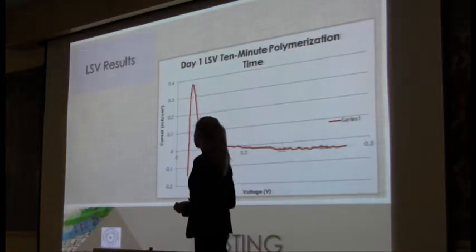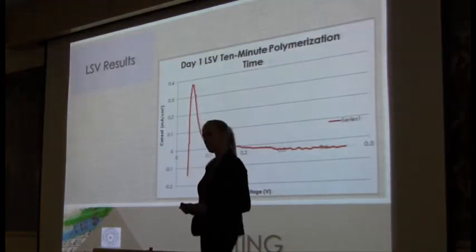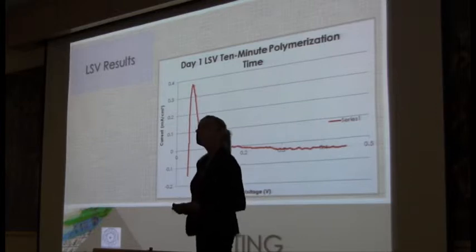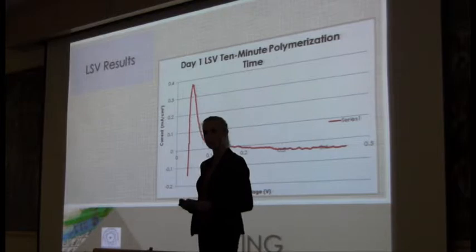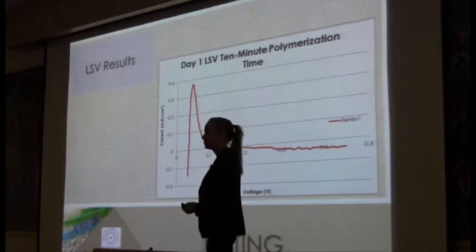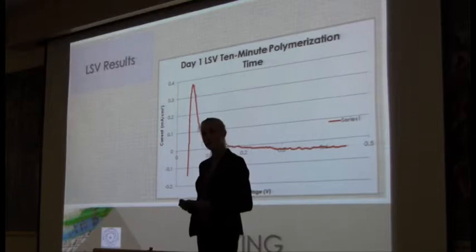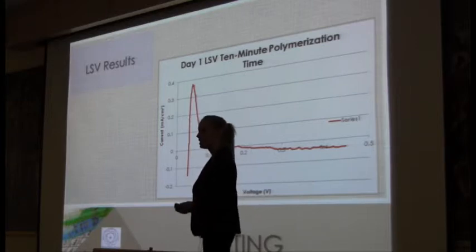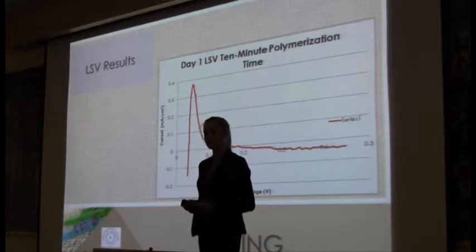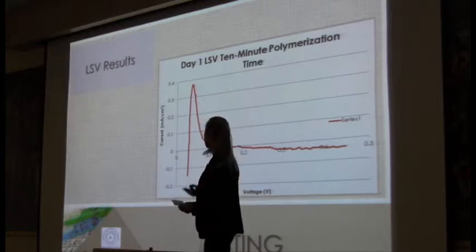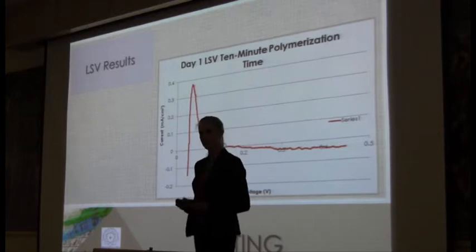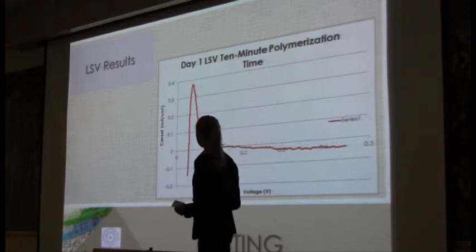So these are the linear sweep voltammetry results for the day 1 10-minute polymerization time fuel cell. From this graph, we can deduce that there is no electrical short in the fuel cell, which is good. However, all other tests, both for the 10-minute and 2-hour polymerization time fuel cells, failed for the LSV test. The reasoning behind this is that dopamine is a capacitor, which means that it can store charge. The storage of electrons means that the LSV test can't give us accurate results. It interferes with the results.